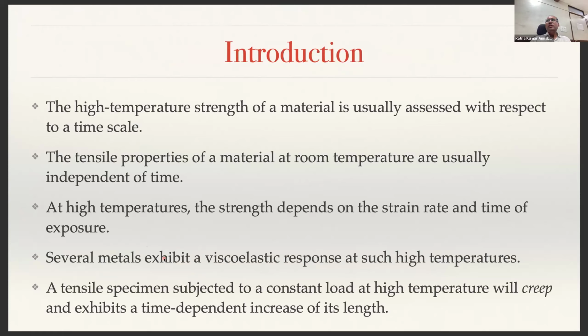So usually, the high temperature strength. When you mention the ultimate tensile strength of a material, we do not talk about temperature. Usually that is mentioned at room temperature. But when you increase the temperature and do the test, the ultimate tensile strength will be lower. It will be reduced. So the high temperature strength of materials is usually assessed with respect to a time scale. What do I mean by that? I will tell you in a couple of slides from now.